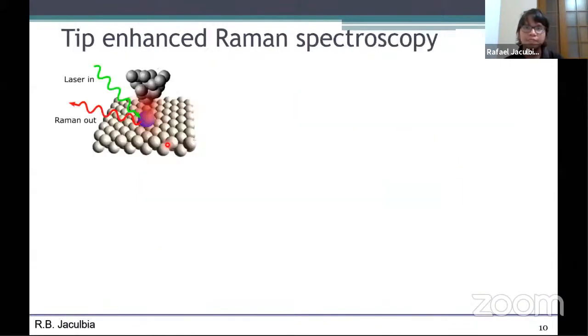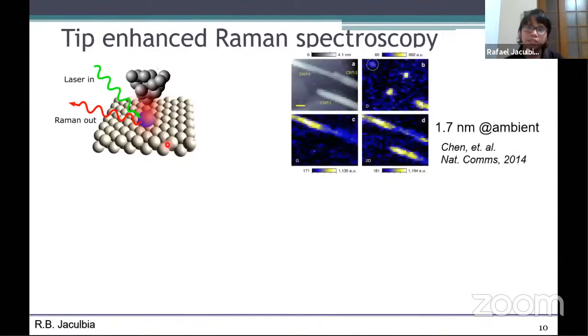So TERS has been used extensively since 2000, and some examples of materials studied by TERS are shown here. This is only for scanning tunneling microscope based TERS. Here is an example of TERS mapping. These are carbon nanotubes. And the authors found that the carbon nanotubes have strong defect signals at the end of the carbon nanotubes, and the spatial resolution they were able to reach is about 1.7 nanometers, even in ambient conditions, so room temperature and atmospheric pressure.